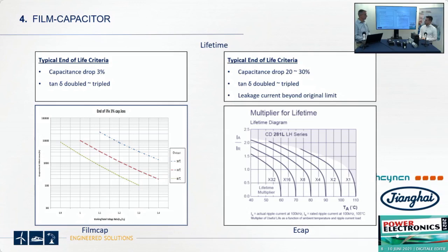Can you name one of your applications you have for this kind of high-end? Yeah, the big inverters for wind energy, each expensive inverter technology where you need a very long lifetime and a long time stable capacitance, which is stable over the complete lifetime. Here you can see the capacitance change over the lifetime. For film capacitors, we have at the end of the lifetime only 3% capacitance loss. For ECAPs, we have at the end between 20 up to 30 or sometimes 50% capacitance loss after the lifetime.